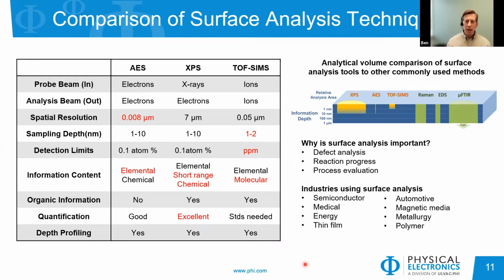Now, all three of these techniques have very good depth resolution, and that's where these shine in these type of applications. The surface information depth is on the order of just a few nanometers up to maybe about 10 nanometers, depending on the technique. As you can see here, TOF-SIMS has a sampling depth of just a few nanometers, whereas XPS and Auger are on the order of about 5 to 10 nanometers.